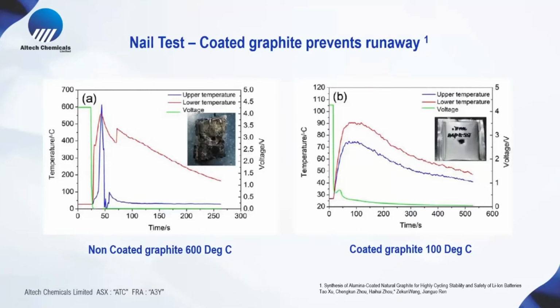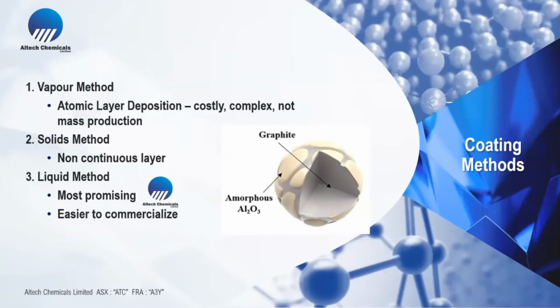This is a great example of the coated graphite with alumina affecting the safety of the battery. On the left-hand side is a nail penetration test. It shows that the battery virtually combusts. Temperatures get up to 600 degrees. On the right-hand side, the batteries are basically intact, and the temperature only gets up to 90 degrees. So coated graphite with alumina helps with the safety performance of the battery.